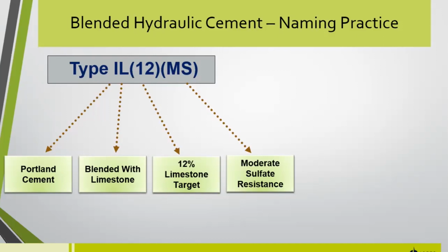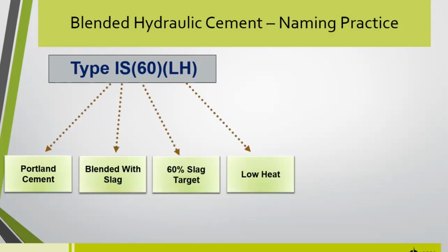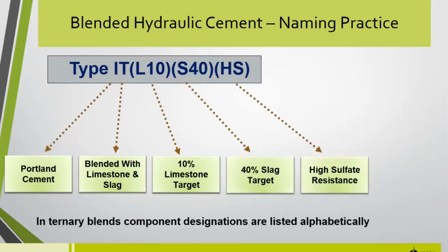Testing is incredibly important, and I don't want to shortchange that. We'll get into that much more in the coming slides here. Here we've got a type 1S or a Portland cement slag blended cement with a 60% slag cement target, and then an LH designation, which would be low heat of hydration. This is similar to a C150 type 4 cement. Here we have a 1T with 10% limestone target addition, 40% target on slag, and HS designation, meaning high sulfate resistance. So when you get your mill reports and you're looking at your components, this will tell you some of the things you need to know. But again, testing is critical here.